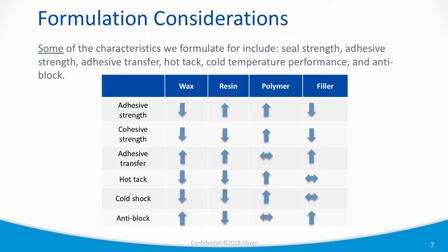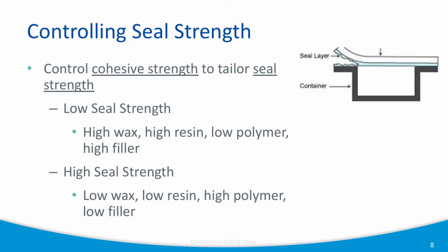And you can see, I won't go through all these, but we have a good idea of what properties, how to get the different properties with the different ingredients. Okay, so again, as we were talking about, you need to control the cohesive strength to tailor the seal strength. And again, from that chart, if you want to get low seal strength, you need high wax, high resin, low polymer, high filler, and the opposite is true for high seal strength.